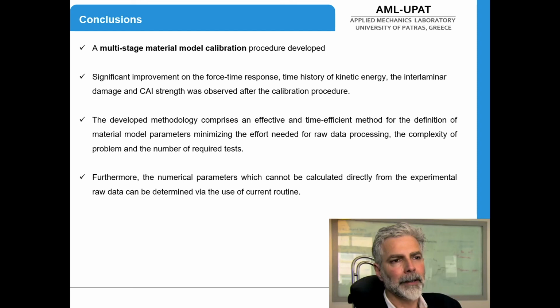very precisely. The developed methodology comprises an effective and time-efficient method for the definition of material model parameters, minimizing the effort needed for raw data processing and the complexity of the problem, in case you would like to have a reliable material model to simulate some experiments. And also some numerical parameters which cannot be calculated directly from the experiments. Using this calibration procedure, you can also have these results in order to use them in the analysis.